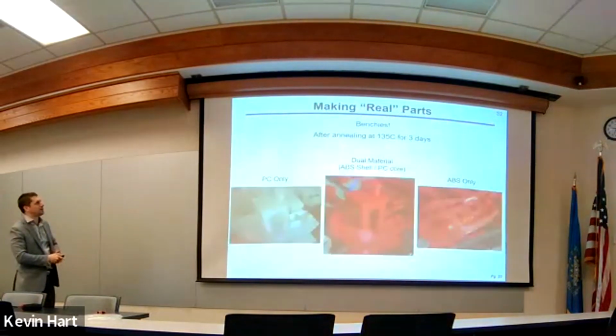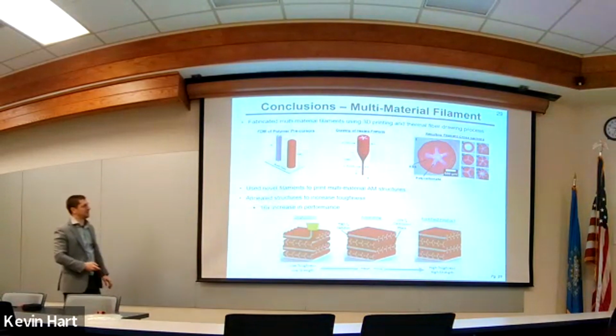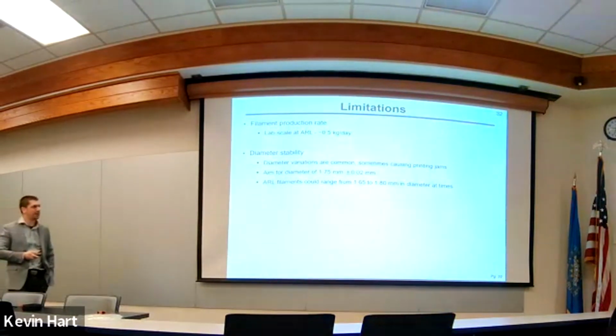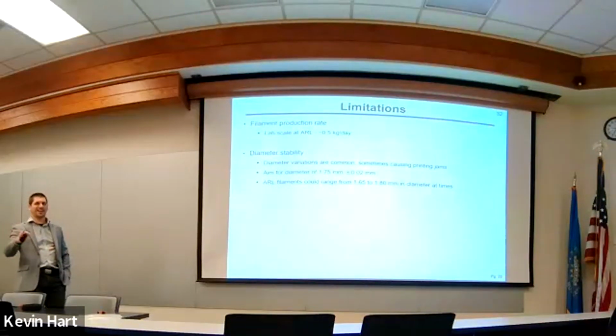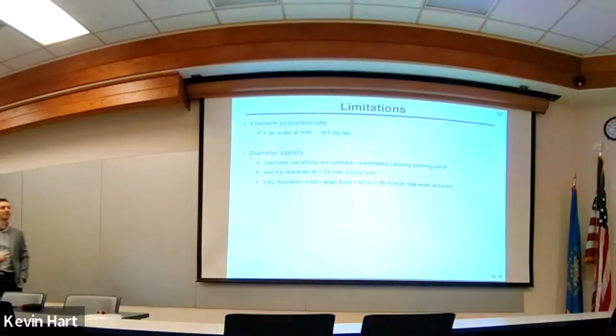unreasonable, but for us that was hard to do because this drawing process is almost freehand. I mean, we had a machine that was controlling the take-up, but it's actually hard to control that drawing process really tightly, like this process here where we're just pulling it down, taking it up. It's pretty hard to control that to the level that we needed. It was close, but not perfect. Okay, ours might be in the range of 1.65 to 1.8 millimeters, which is suspicious. All right, sus, as they say.